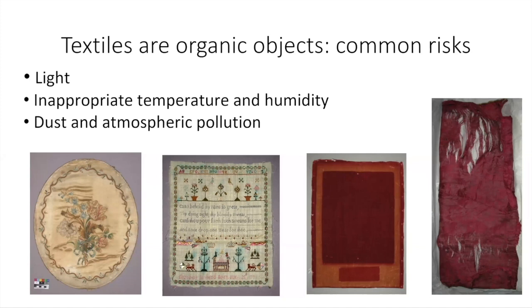Fluctuating levels of humidity are particularly damaging to textiles. The textile fibers expand and contract with changing levels of humidity, and this leads to what we call a fatigue mechanism of damage. So this embroidery on the left is tacked onto a wooden board, and as it became more brittle over the years, it was no longer able to withstand the stresses of continuing expansion and contraction, and it has split. It's split here and here.